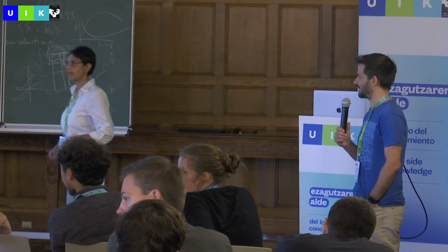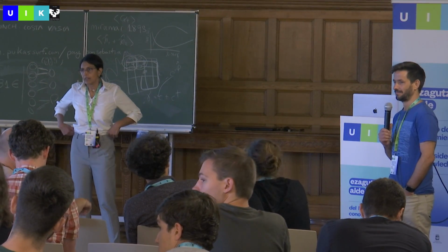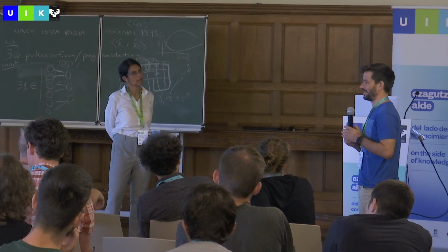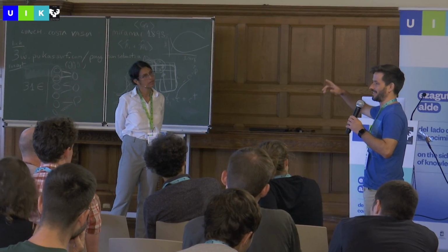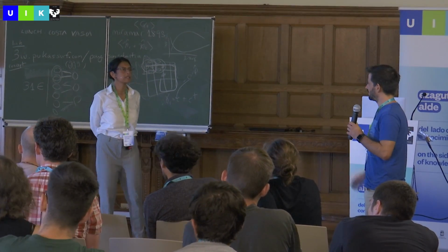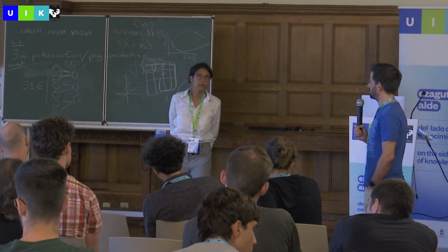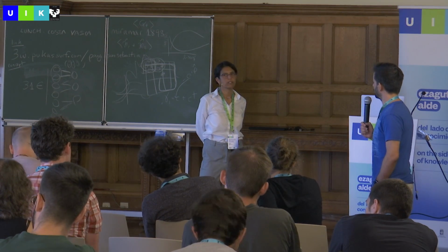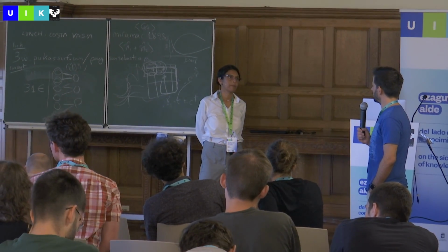I asked if somebody had measured QPI on the surface of quasicrystals. Yeah, but you could still see, let's say, a long wavelength excitation, even if it's gappy, you should see a dispersion. It depends on how insulating it is. If it's very insulating, it's very hard for us. But we are able to see semiconductors. It depends on the gap magnitude. If it's a few hundred meV, we might be able to tunnel into it. If it's many electron volts, we have a problem.